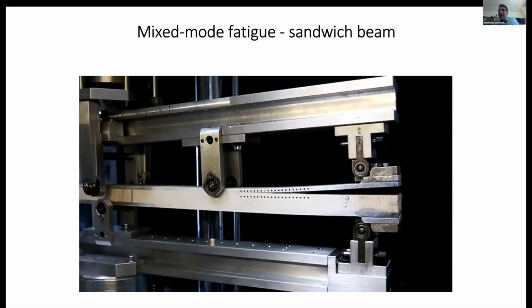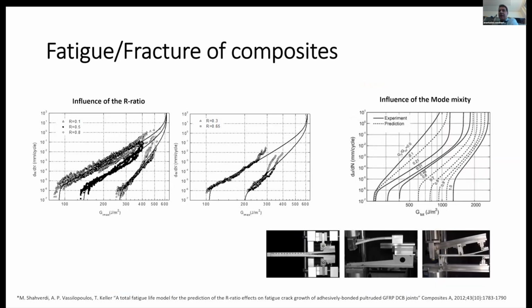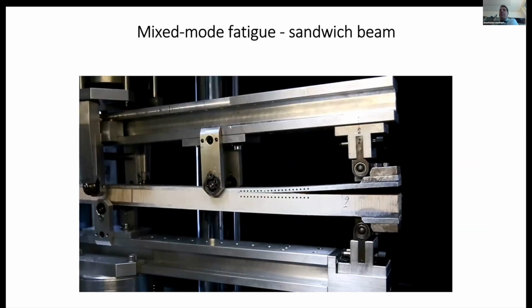So to get this video and to get results that give you curves like this, you need to run the test for 4 or 5 million cycles. At 5 Hertz, 5 million cycles means around 10 days. So be patient enough to be there 10 days, measuring the crack, investigating if the test is progressing well. Cross your fingers that you don't have a failure in electricity or whatever else. And this is how we do fatigue investigations.